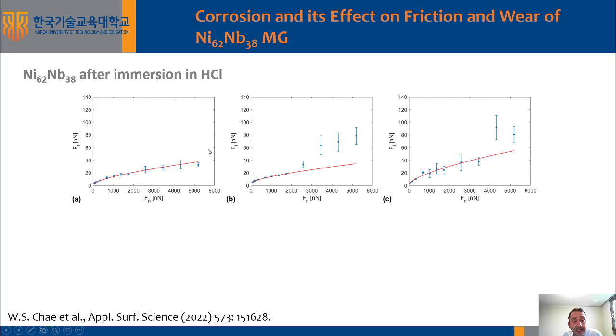Now, even more interestingly, if we now grow a niobium pentoxide, we find that we completely suppress abrasive wear. We now only have shearing friction. Now, these points here are rather outliers that correspond to the transfer of sample material onto the tip, and maybe again the discharge of this transferred material from the tip.